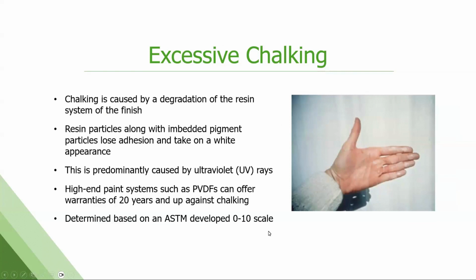Excessive chalking. This is one most people aren't all that familiar with, and it's just what it sounds like: you get this white chalky residue on the surface. You can run your hand on it. It comes off on your hand. This is degradation of the resin or polymer system, usually by UV attack. So that long polymer chain is breaking down into little smaller sections. And remember, it's got the pigment attached to it. And now it can just come off the surface. It's not tied up in that film anymore.